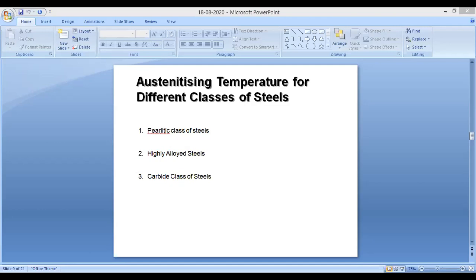For that, these steels on slow cooling, as in casting, or even on heating to 500 to 800 degrees centigrade, precipitate carbides, generally on the grain boundaries of austenite. Such carbide precipitation causes a decrease in ductility and impact strength, and depletes the regions close to grain boundaries of, for example, chromium in stainless steels, decreasing the corrosion resistance of the regions causing intergranular corrosion. Presence of double phase instead of single phase austenite further accelerates corrosion by forming micro galvanic cells.